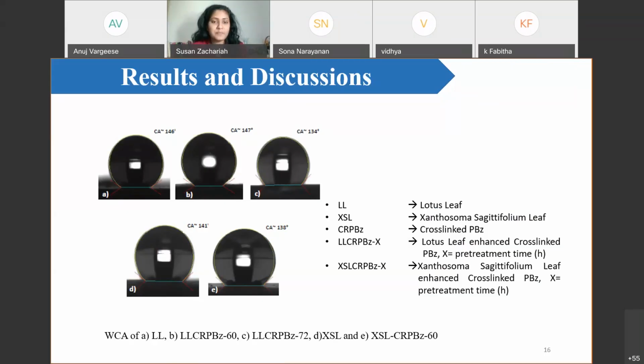It is 147. To check if we go beyond the time, like from 60 to 72, we checked and found the contact angle reduced. We have used 40, 50, everything, and the best one obtained is at 60 pre-treatment. So we made it the optimum time for pre-treatment. In the same way, for the Xanthosoma sagittifolium leaf, the contact angle was less than the lotus leaf. It is 141, and with the same 60-hour pre-treatment, it gave 138. So the best sample which we obtained is lotus leaf based cross-linked PBz treated for 60 hours, and the contact angle was 147.